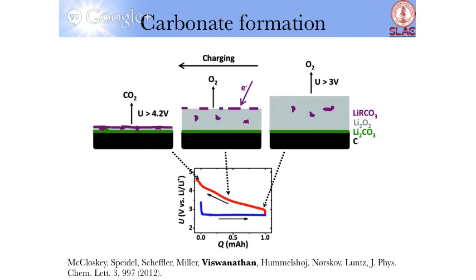What's really interesting is that when you're trying to charge the battery, you have this rising tail. We attributed this to a decomposition process that coats the film on top of the lithium peroxide. This means you have a constant current boundary condition — you have to drive the reaction at a certain rate, but the number of reactive sites has gone down. So you have to raise the potential to drive the reaction faster at the sites you have. Along the accessible sites, you need to drive the rate faster — giving you this rising tail.